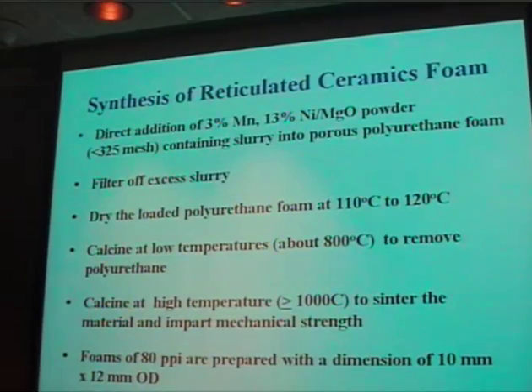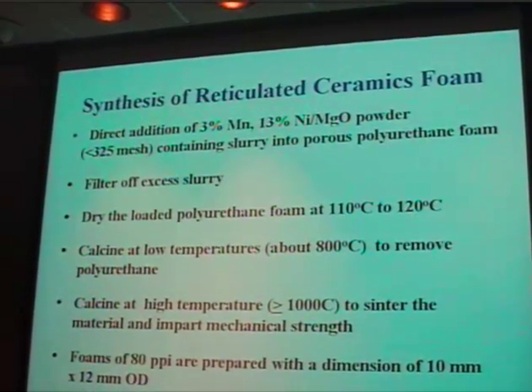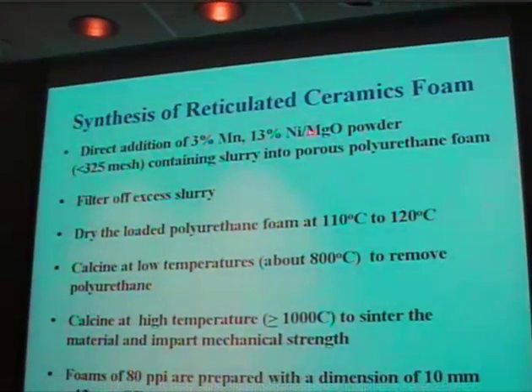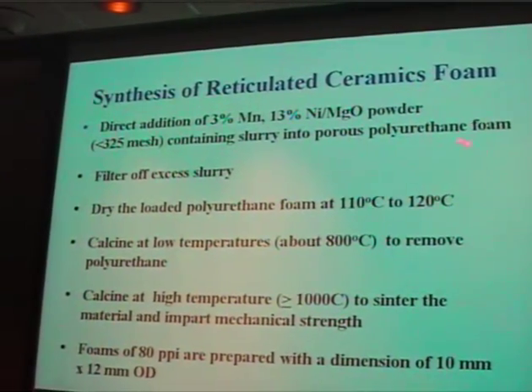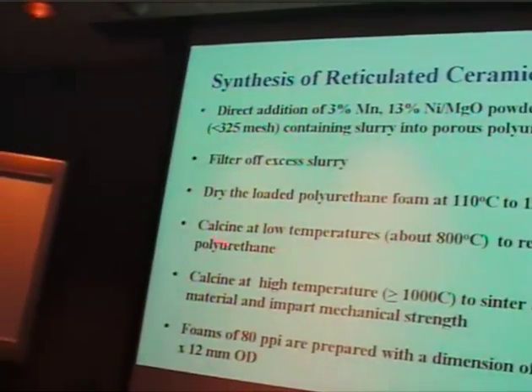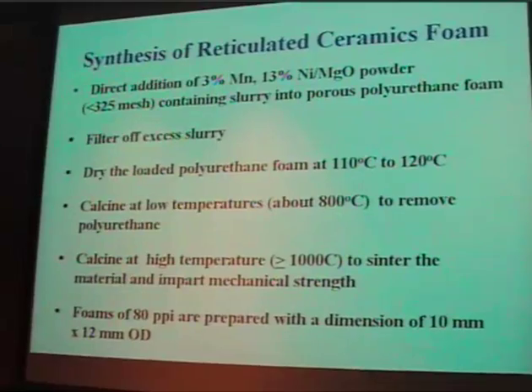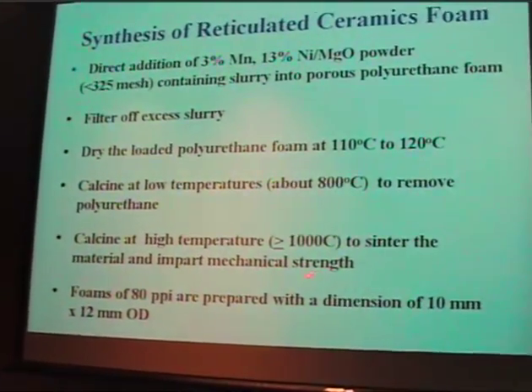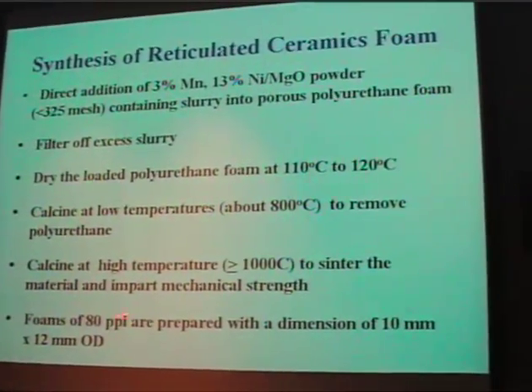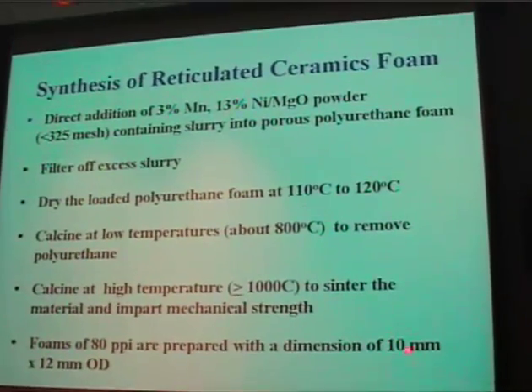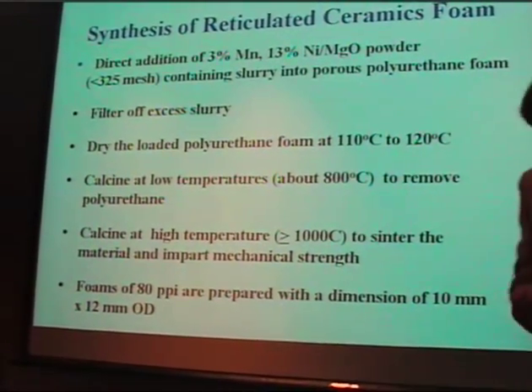All right, so the program began with a lot of screening, identifying opportunities of where to develop new catalytic systems that would be competitive with rhodium. We felt like we were comfortable moving forward, in this case with a manganese promoted nickel MgO. We wanted to get it into a more practical three-dimensional form. And one approach that we did was to form reticulated ceramic foams. So basically taking the powder, putting it into a porous polyurethane, filtering off the slurry, drying it, calcining it, basically at relatively high temperatures to give it mechanical strength. So we ended up with a form that was roughly 80 ppi and of the diameter and length appropriate for our quartz reactor.